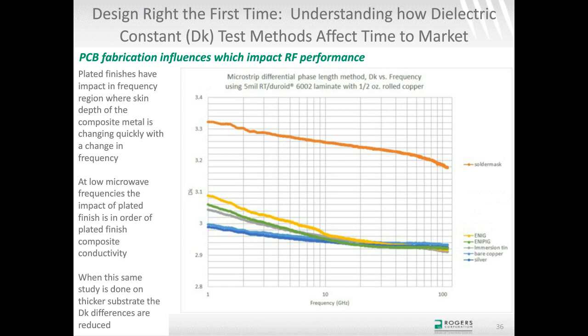and it's having an effect on the phase response. And the reason I bring this up really is because I've had issues with nickel varying in thickness, which is not unusual, and having an effect on a base station power amplifier at frequencies down around the range that I'm showing here, that you can get this variation. So at lower microwave frequencies, the difference of plated finish and the thickness variation that's normal for some of these thicknesses could actually impact the phase response.